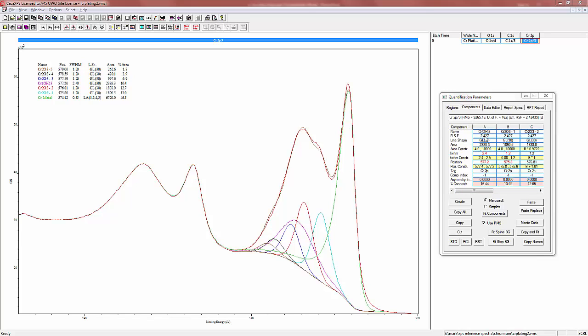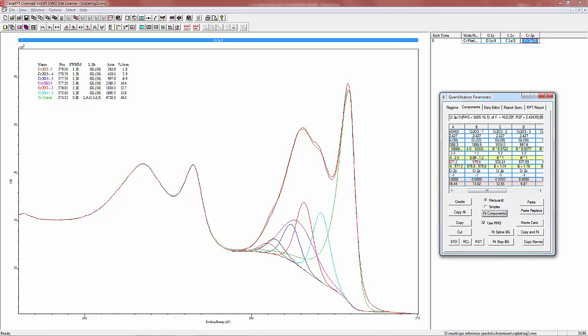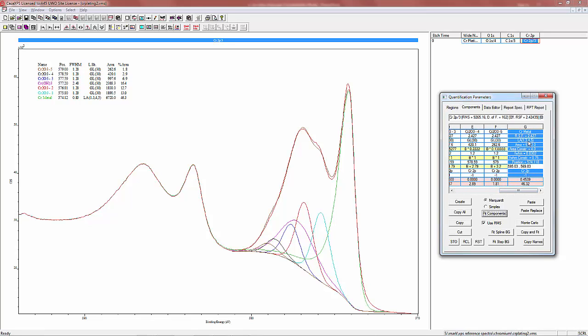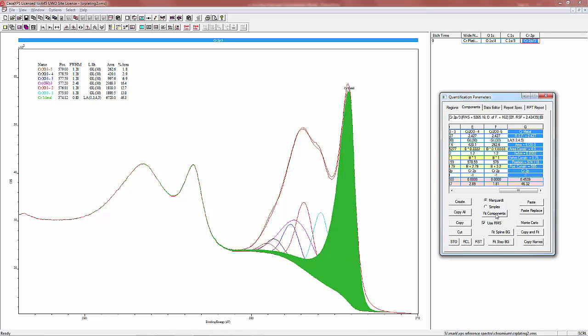We can see in CASA XPS that the chromium hydroxide — the large purple peak — has a FWHM of around 2.5 eV, positioned at a binding energy between 577.2 and 577.4 eV. For the five peaks of the multiple split chromium oxide structure, we start with the first peak and constrain everything to it: the FWHMs are all equal to that original peak, the positions are all based off where that peak is, and the areas are all ratioed to the initial peak. For the metal, we use an asymmetric peak shape with its position set within the previously defined range.